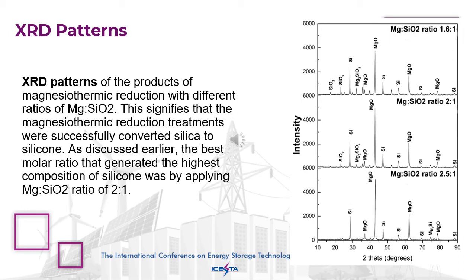XRD pattern of the product of magnesiothermic reduction with different ratios of magnesium and silica. This signifies that the magnesiothermic reduction treatments successfully converted silica to silicon. As discussed earlier, the best molar ratio that generated the highest composition of silicon was applying a magnesium and silica ratio of 2:1.